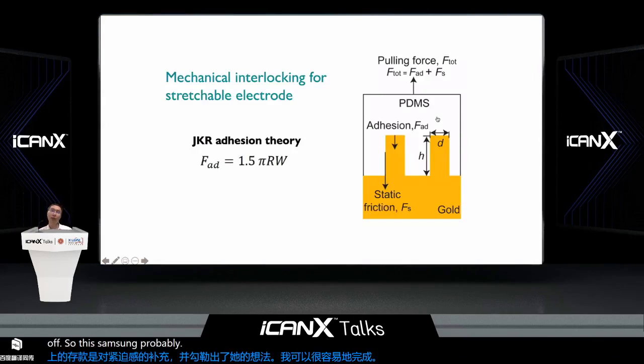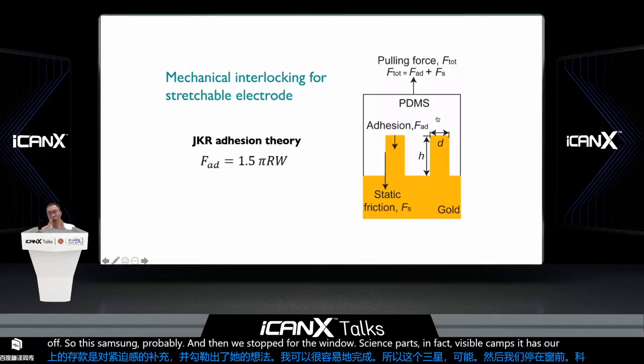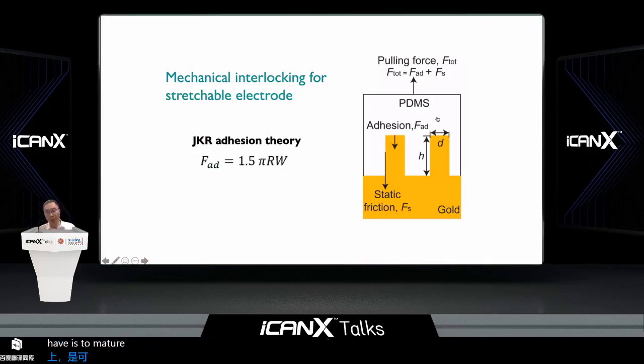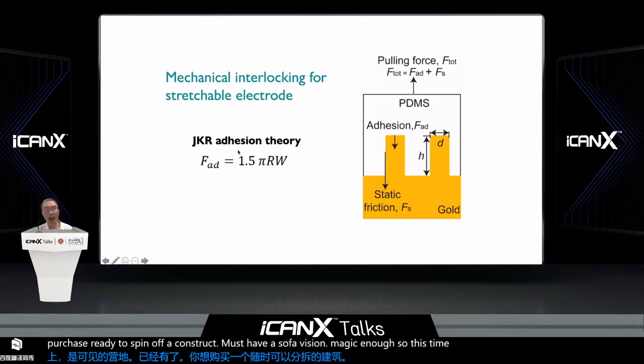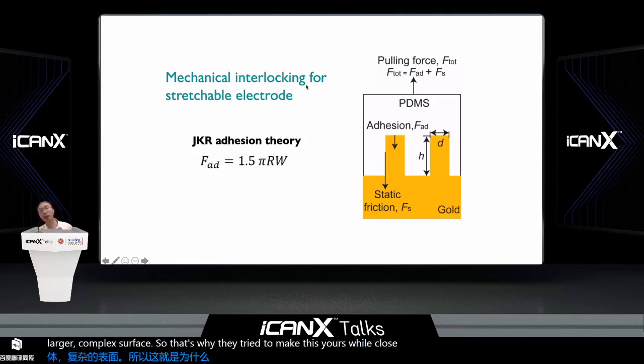Then we start from the fundamental science. Physical chemistry already tells us that if you want two materials to not peel off easily, they must be close together. You must have large enough adhesion energy. This is called JKR adhesion theory. To increase adhesion force, you must have a larger contact surface. That's why we try to make the two materials in closer contact. That's what we call the mechanical interlocking model.